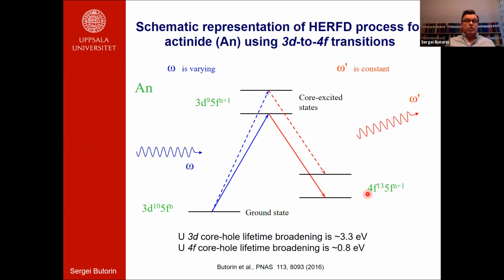And if we have an X-ray emission spectrometer, we can tune it to the energy of the 3d to 4f transition. Usually it's done by tuning it to the maximum of the emission line, and then counting only the photons of this energy while scanning the energy of the incident photons. Then we record a spectrum which will be broadened by the 4f core-hole lifetime. The difference in core-hole lifetime broadening is actually quite large. The 4f core-hole lifetime broadening is 4 to 8 times smaller than the 3d core-hole lifetime broadening, according to different estimates. That should improve the resolution of our spectra.